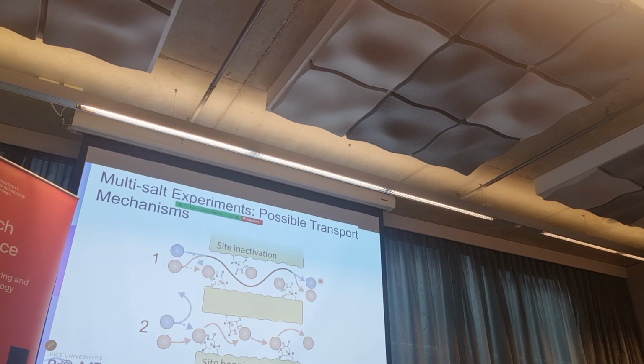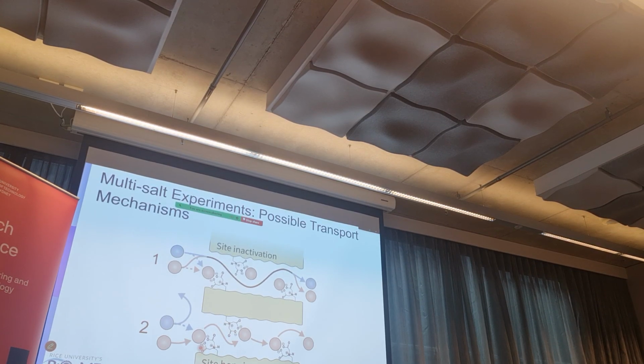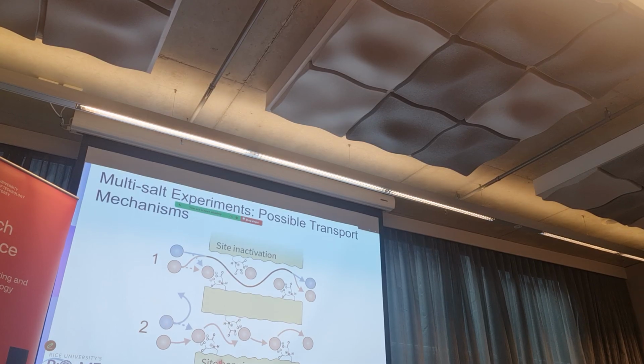The other possibility is site hopping, more like a potassium channel. If the binding isn't super strong, we hypothesize the copper will bind and hop from site to site, while magnesium won't be able to do this because it doesn't fit and doesn't have strong binding—so again you wouldn't see separation.